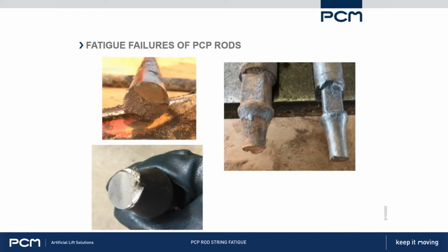Just some pictures. This picture on the top left here is a good example of a classical fatigue failure. And what we see here, there's two distinct regions. The first one is very smooth. That's where the crack was growing. So this is where eventually a crack was forming, and it grew this big. You can see the line where it got to, and at this point, the remaining material was no longer strong enough to carry the load, and it broke. And that final fracture is the rough surface.